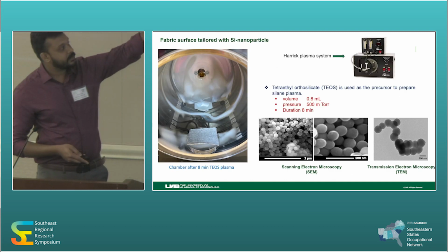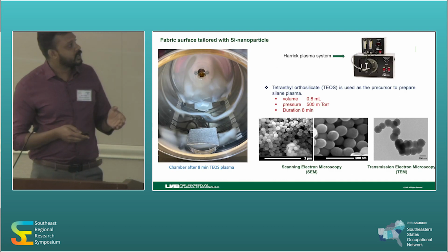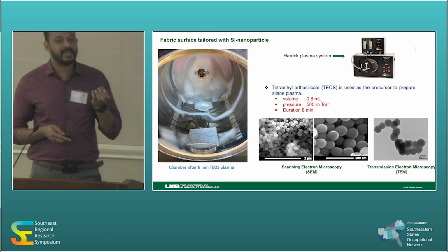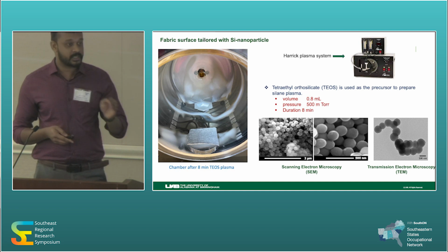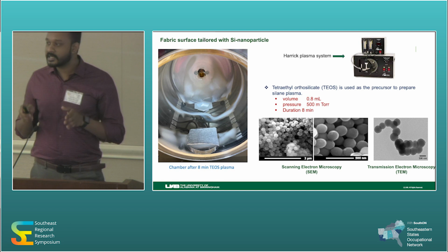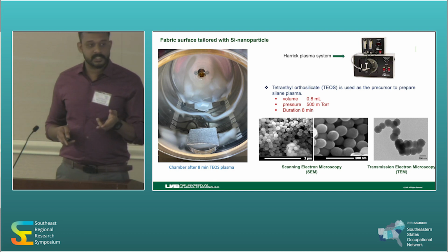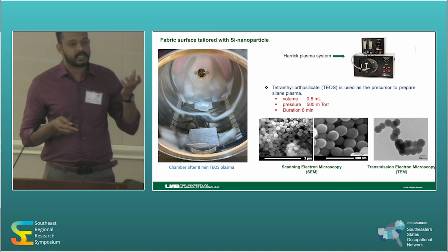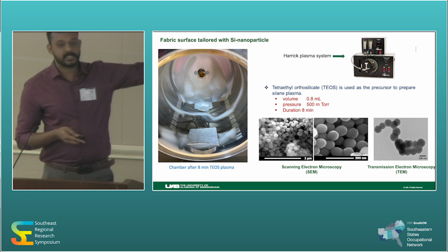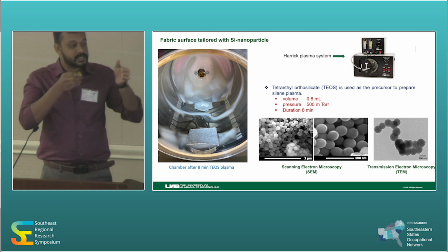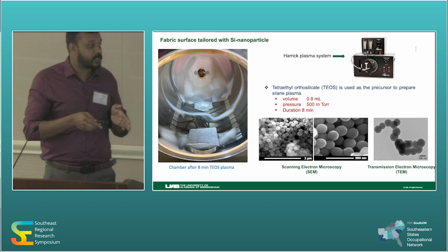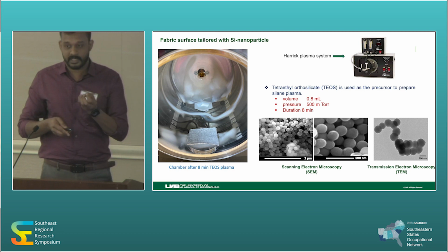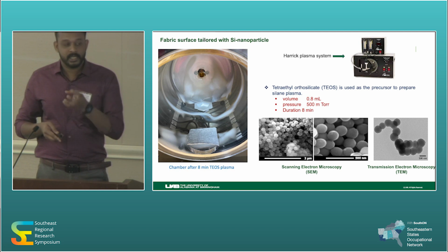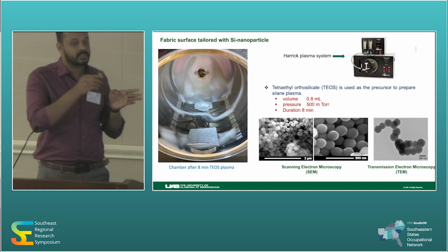Then this is the plasma chamber that we're using, a Harrick plasma system. The volume of TEOS we are using is 0.8 ml, so we are not using a high quantity of chemical. It is a green technique. The duration is 8 minutes. That is optimized; we tried different times, and the better coating happened at 8 minutes. Then the pressure is 500 millitorr. Exactly, 500 to 1000 millitorr is an effective pressure to create a silane plasma, since silica nanoparticle production is high at 500 to 1000 millitorr.